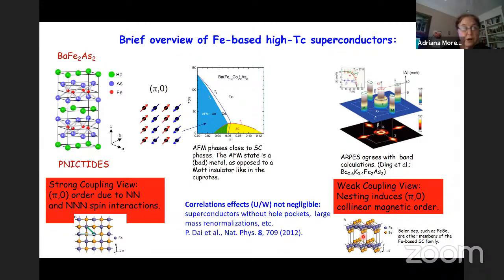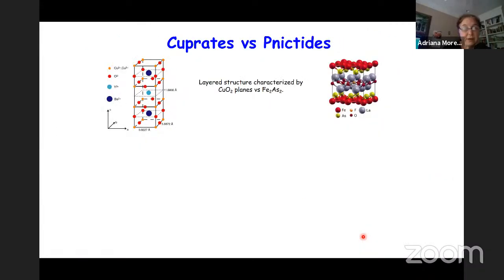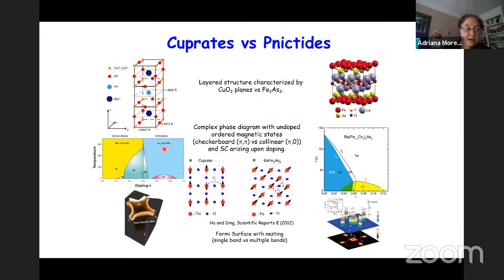So before moving on, let me rapidly make a comparison between cuprates and pnictides. Both materials have planes, copper oxygen versus iron pnictide or iron chalcogenide. Both materials are magnetically ordered in the undoped case, but the cuprates have this checkerboard magnetic order, and they are Mott insulators.